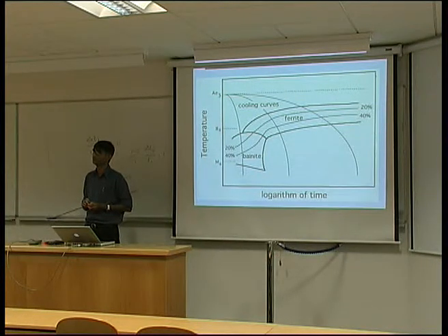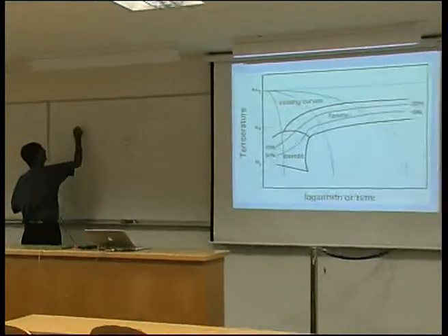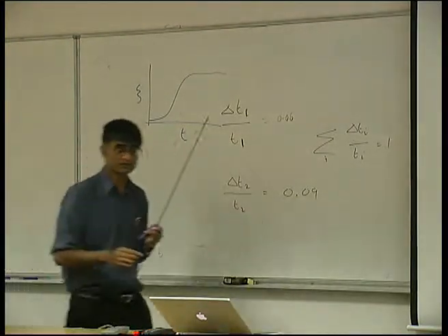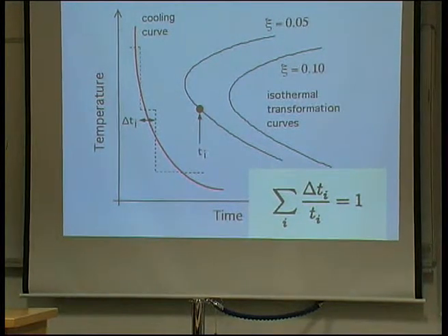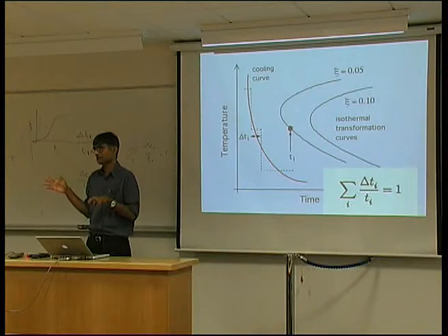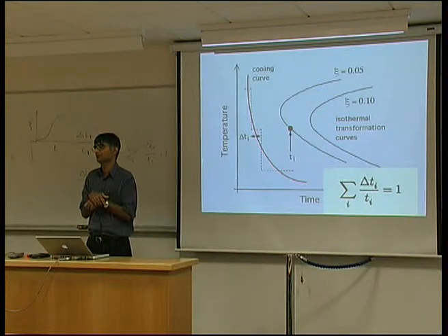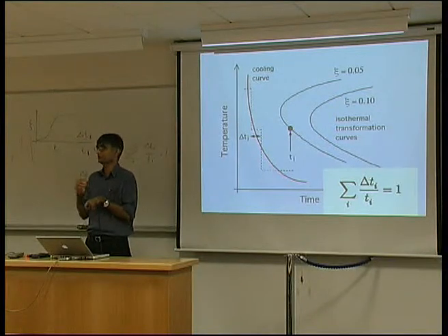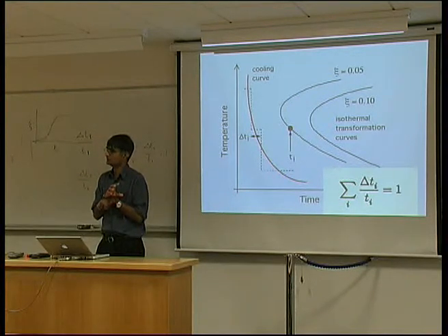So is it possible to reach any level of transformation? Yeah, you've got the whole of the curve, so you can pick the level of transformation for which to plot this curve. Presumably we're taking longer now because we're cooling down, so I wonder whether we can really reach any level of transformation. Yeah, if you choose your cooling conditions correctly, you can reach any level of transformation, the ultimate being the slowest possible cooling. Correctly meaning very slow, so you achieve equilibrium at each temperature. So is everyone happy with how to convert isothermal transformation to continuous cooling?